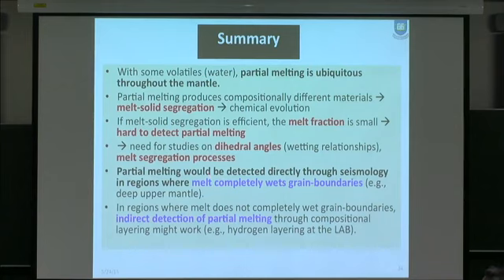However, under those conditions where melt completely wets grain boundaries, then you could do it. So it is very important to conduct laboratory experiments to study dihedral angles, as we did several years ago. This study must be extended to transition zone and lower mantle conditions. In regions where melt does not completely wet grain boundaries, indirect detection of partial melt might work. One example is the lithosphere-asthenosphere boundary, and some other regions. If you have some inference of chemical layering, that is very strong evidence for partial melting, because chemical layering is impossible for the convective mantle without large-scale segregation of the materials. I think I should stop here.